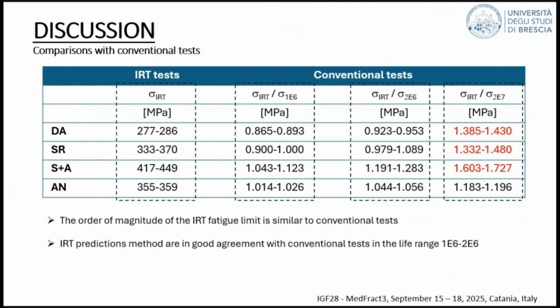The first one is that if you test at 20 million cycles, basically you are testing the material with low stress. Low stress means that the thermal response that you will activate will be limited. So you will face very small thermal variation, very small temperature variation. So it's more difficult to catch this variation accurately, or maybe it could be a limitation of our setup.